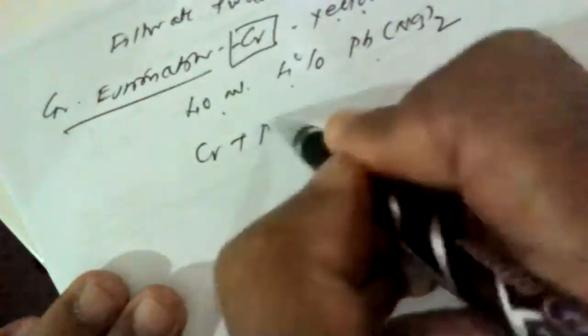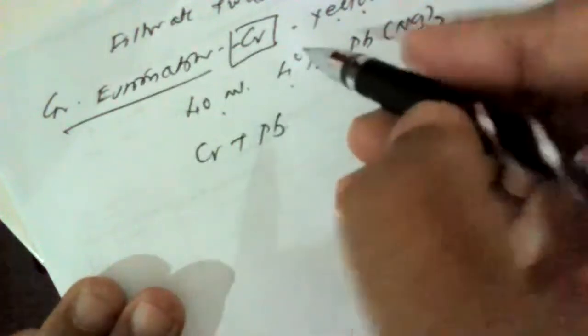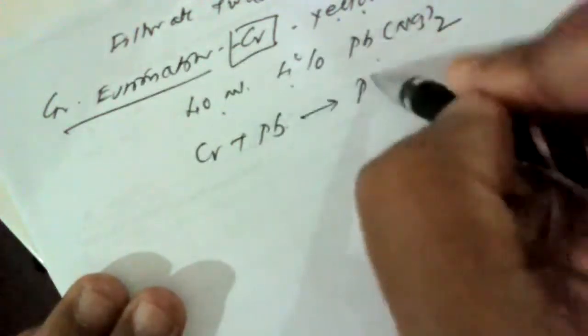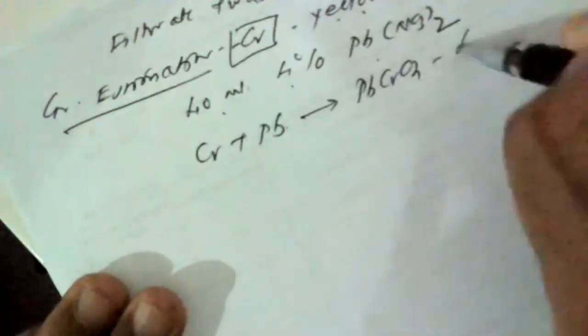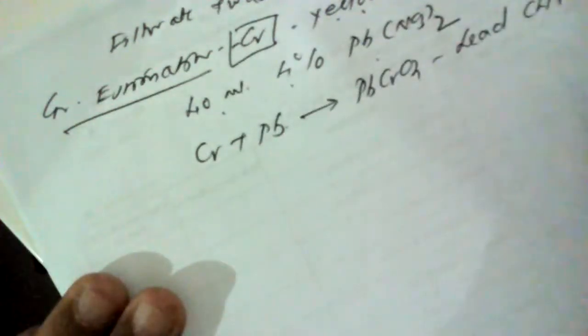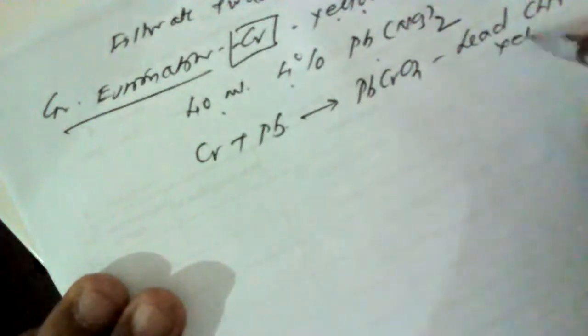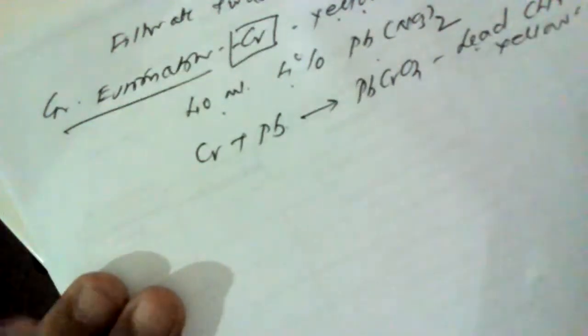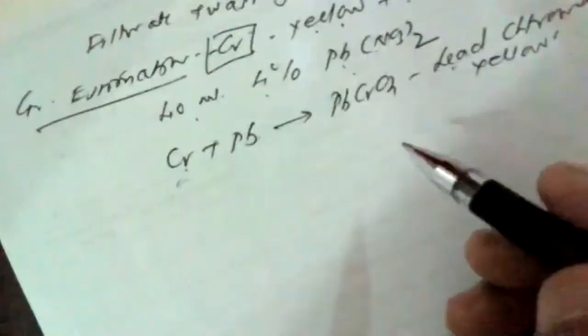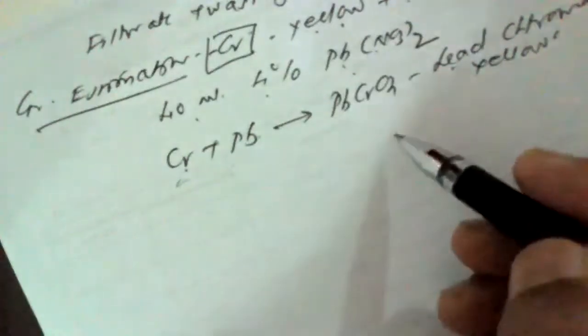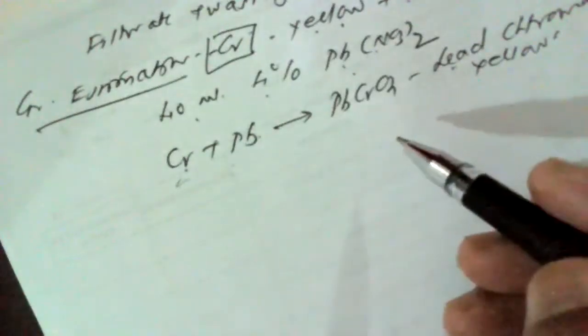So by adding 40 ml of 4% lead nitrate solution to this yellow solution, the yellow solution contains chromium, and this lead nitrate contains the lead radical. So here we have obtained PbCrO4, known as lead chromate, which is canary yellow in color, a very fine yellow color. The lead radical from lead nitrate combines with chromium from this yellow filtrate and forms lead chromate. This is how we have precipitated the chromium.